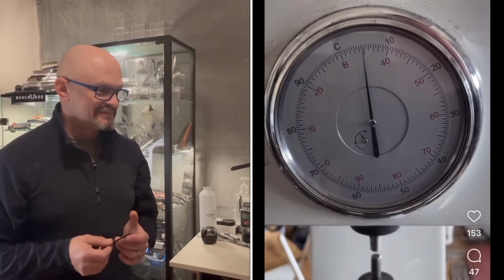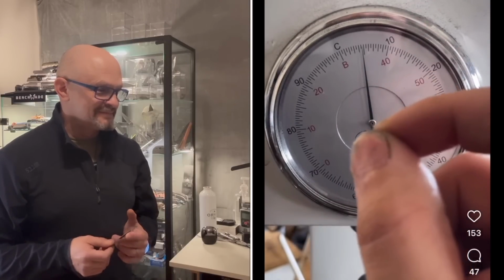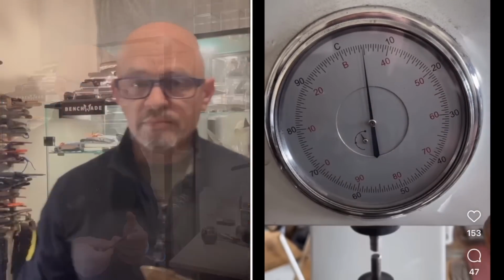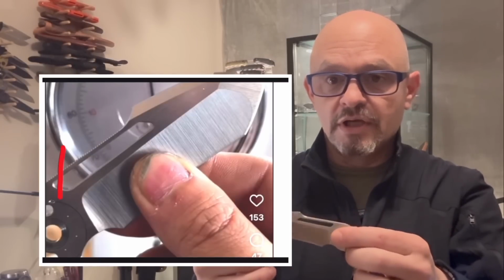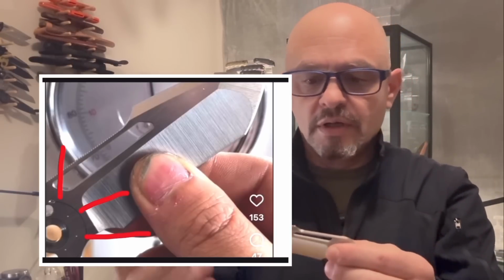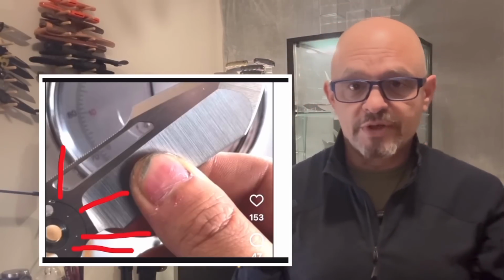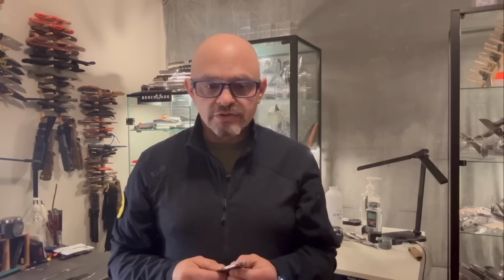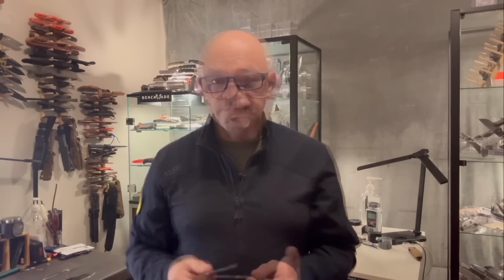It really matters how right you are, in a sense. If you want to say this one is out of spec, a little bit lower than it should be, he's correct. But there's a big difference between being 62.6 HRC instead of 63 and being 59 HRC instead of 63. I'm not sure whether he was running out of film, but when he showed the knife, there are 5 or 6 pokes from the Rockwell tester, and I couldn't tell what these measurements were because he just decided not to mention those. So all we have is one measurement that he did on camera, and that was 62.6, which is very close to the 62.5 that I got here.